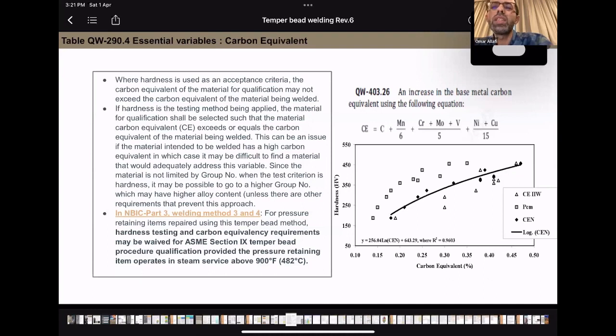And sometimes it is difficult. Why? Because when you have high carbon, high chromium, or high Mn values in the steel, you cannot find a test coupon that has a higher carbon equivalent value. So when you have a carbon equivalent for the base metal, the test coupon should have a similar or higher carbon equivalent value in order to be qualified for welding this base metal.